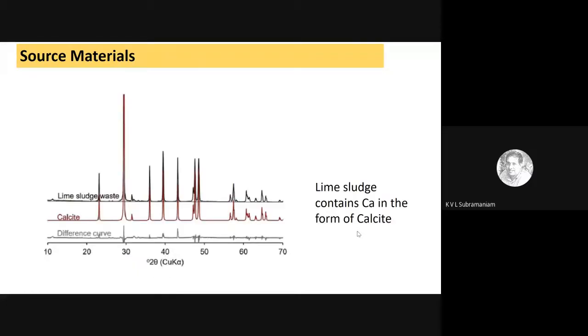So now let's look at these materials individually to make sure that they are present in the reactive forms. If I look at the XRD, X-ray diffraction signature of my lime sludge, most of it is present in the form of calcite. If you see the graph, the spikes shown in the maroon say that most of my lime sludge is available in the form of calcite. Calcite is nothing but calcium carbonate, which is actually excellent because this is exactly the source that we use for making cement in the form of limestone rock. So that calcite is coming from this lime sludge.